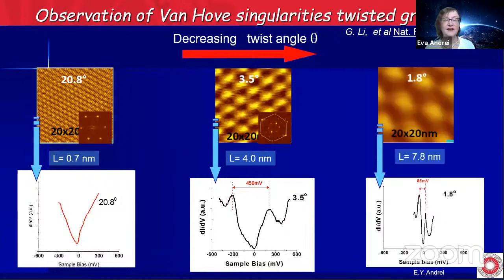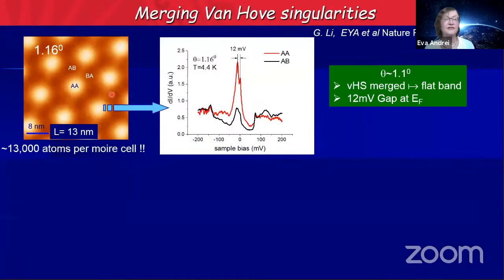And then we keep decreasing the angle. Now at 1.8 degrees, these peaks have moved in even more. They've come closer together. And look, they become sharper as we move in. And here we've reached what we call the magic angle, 1.1 degrees. And the two peaks have merged into one. This is a flat band that has a high density of states and it's quite narrow in energy. The Fermi energy is sitting within this flat band and we see a small gap opening. So that is suggestive of a correlated state.